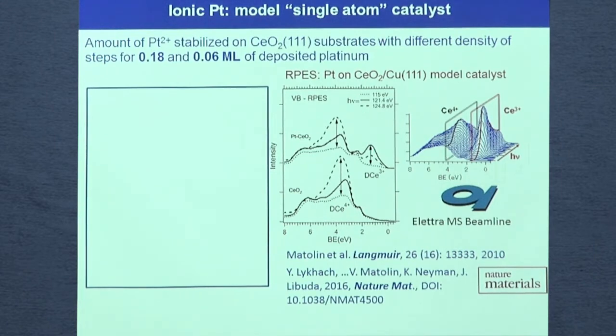Other thing is we can check how it depends on the stoichiometry of cerium oxide. As I said, we are using resonance spectroscopy, which is maybe 100 times more sensitive technique than the standard XPS. This is the so-called 4f-4d resonance. There is no time to explain. However, if we are tuning the energy of light at the synchrotron and measuring the concentration of cerium 3+, we are going to the maximum in the valence band, and at 2 eV and at 4 eV we have another maximum for cerium 4+. Well, so we are able to check it very well.